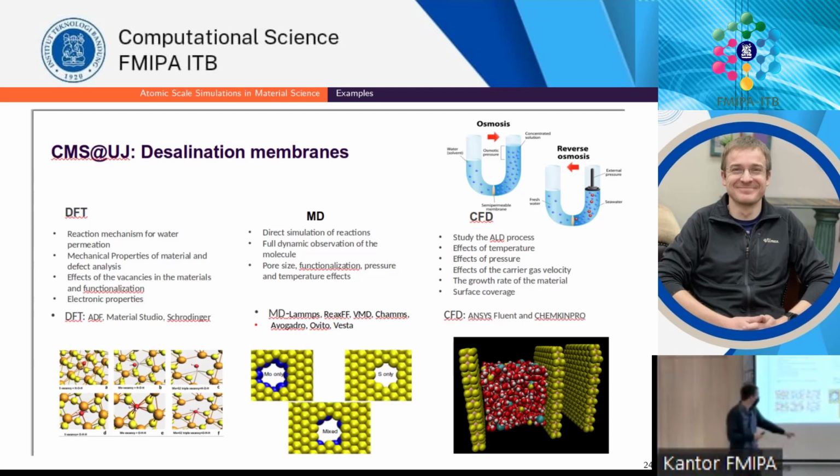So you create a reactive site by producing a defect in the molybdenum disulfide, and you see whether the water, for example, would have any meaningful interaction, right? Because that, of course, could mean that you have the clogging up of your porous membrane, right? Or some other effect which would change the diffusion coefficient, right? So we don't want that. Apparently, they did not find such an interaction, so everyone was happy with the measured results.